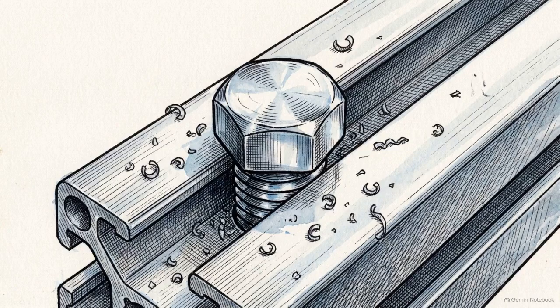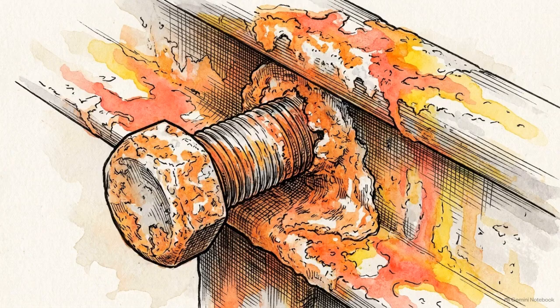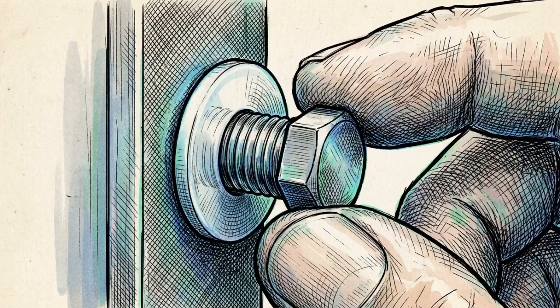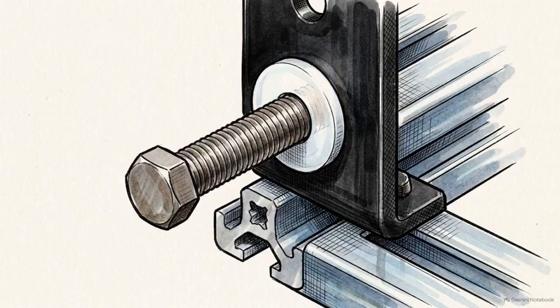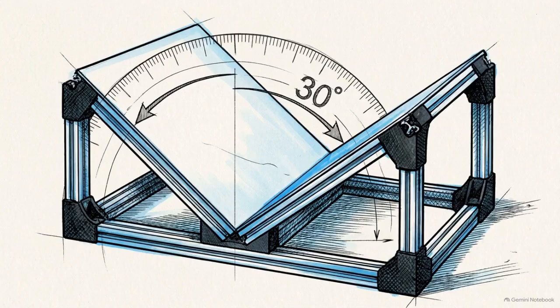If you drive bare steel bolts directly into the raw aluminum extrusions, the ambient humidity causes the metals to react, and the joints will rapidly rust out. The fix takes 2 seconds. Slide a nylon isolation washer onto every stainless steel bolt before you thread it into the frame, entirely separating the two metals. We build this skeleton as an inverted V, tilting the collector wings inward at exactly 30 degrees.